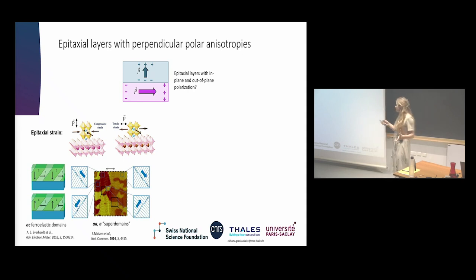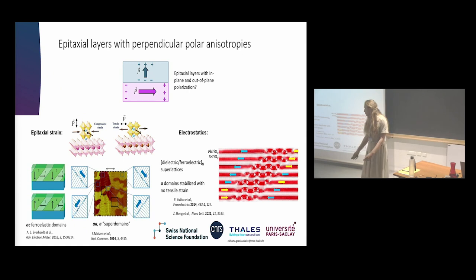Another route would be to consider electrostatics. These are the famous dielectric-ferroelectric superlattices, where we have lead titanate, which is ferroelectric, and STO grown in short periods. Essentially what happens is that STO is dielectric. It cannot really screen the out-of-plane polarization of PTO, and then PTO is forced to go in plane.